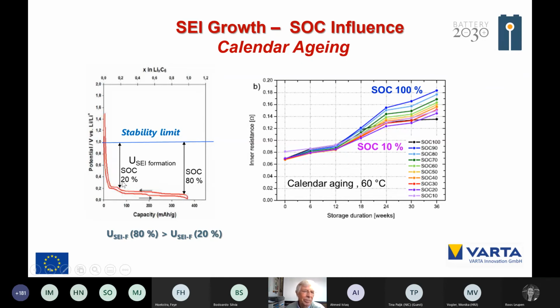And that is the potential of the graphite electrode at a state of charge of 20%. So here you have a higher potential difference at 80% to the stability window than in case of 20%. So that potential is lower. And therefore, the reaction rate at the graphite electrode with a state of charge of 80 or 100% is larger than the reaction rate of the graphite electrode with 20%. And you could see that here, that the graphite electrode with 100% state of charge is aging much faster than in relation to 10%.